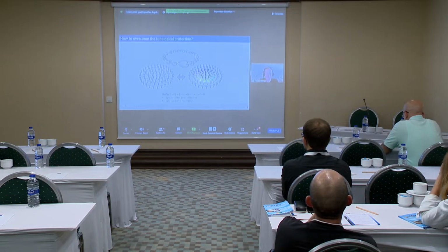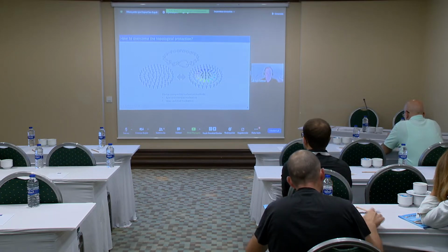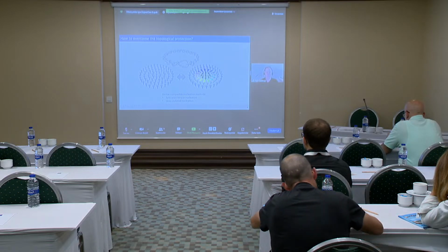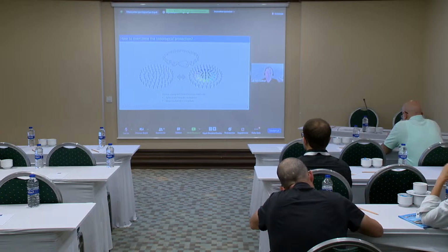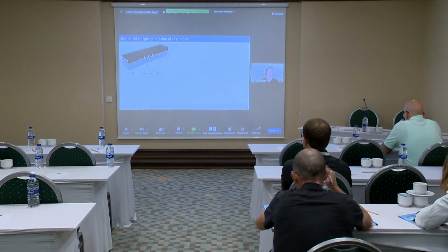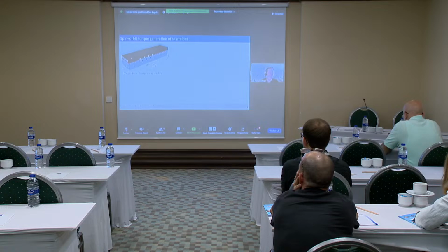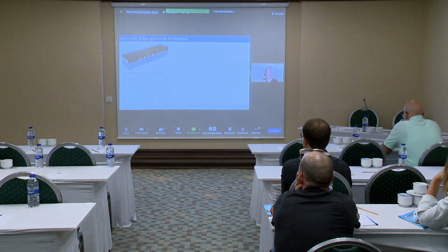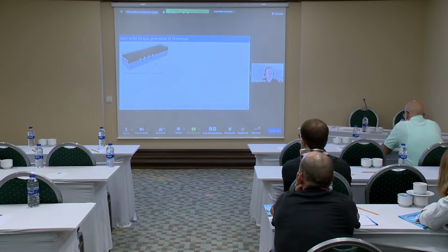For this particular talk, I will focus on two device-compatible mechanisms that allow such nucleation in a fast and deterministic manner. The first one is spin-orbit nucleation, and the second one is laser nucleation. For spin-orbit nucleation, we need two ingredients, basically. The first one is vertical inversion symmetry breaking of the material. In this case, you have a superstructure where the first layer is a heavy metal, which can also be a topological insulator, where you have strong spin-orbit interactions. On top of that, you have a magnet. And then the third layer would be a different material. It's not magnetic, but also not the same as the one below.